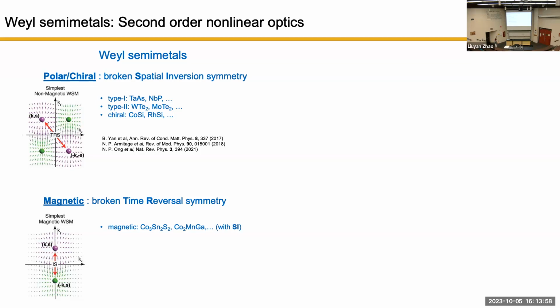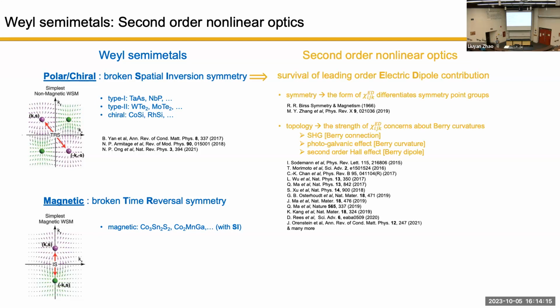Okay, so for the case of breaking spatial inversion symmetry, there are many, many examples. Like they can be either polar or chiral. Both of them break spatial inversion symmetry. And what's more exciting to optics people of these compounds is that there's a whole list of theory and experiments done in these non-centrosymmetric Weyl semimetals. And they include SHG, photocurrent, and second order Hall effect measurement, and so on and so forth. The reason for them to look into this is because now the inversion symmetry is broken. All the second order nonlinear processes that are mediated by electric dipole are going to happen. And more importantly, if you make their frequency low enough, the strength of them is actually proportional to the Berry phase of this Weyl semimetal. Essentially meaning that you can use nonlinear optics to not only see the symmetry of the material, but also see the wave function topology of the material. That's the whole driving force of this much research in these non-centrosymmetric Weyl semimetals.